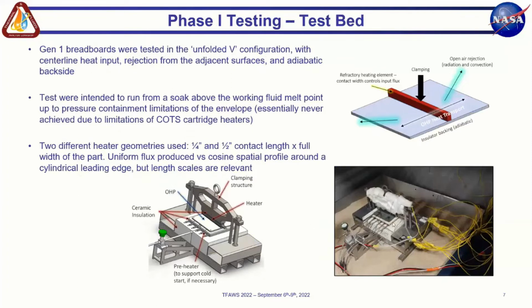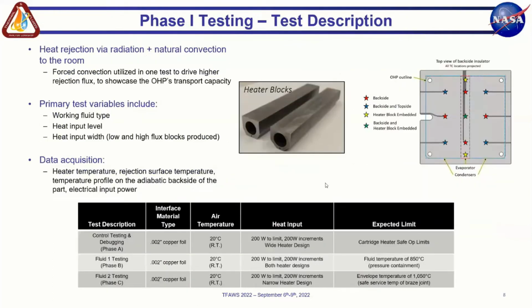So here we see a picture of that phase one test bed, the CAD and the physical one. We worked with two different heat input geometries, a 1/4-inch long contact patch and a 1/2-inch long contact patch formed by the physical interface with these molybdenum blocks that we used with commercial off-the-shelf Inconel sheet. Cartridge heaters were fed inside. We applied electrical power that was driven into the OHP evaporator at this clamped interface. TC map shown on the right. We have TCs in the heater block and on the physical rejection surface, but also on the backside where we have that adiabatic boundary, but the ability to place TCs there as well.